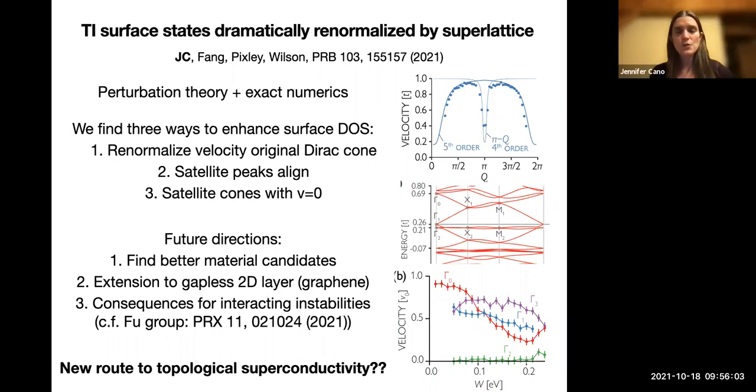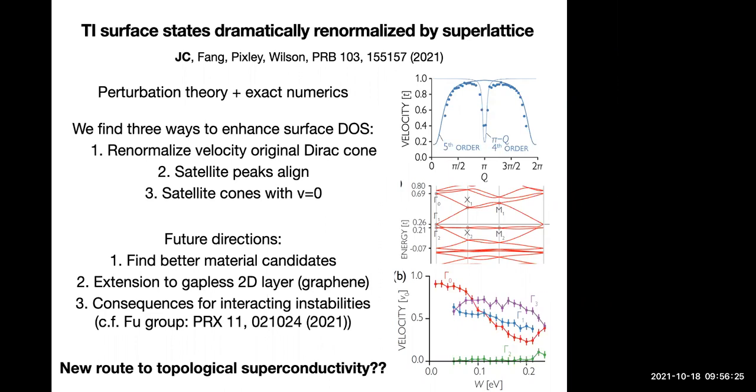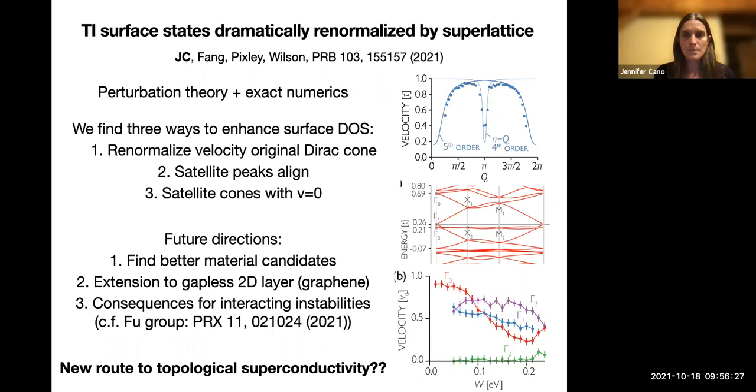Right, exactly. So we have some results in this direction already. It's a different calculation where instead of having a potential, we would actually keep the interlayer coupling. So you tunnel TI to say graphene and then back. And so that's why we expect that you would get something different, because it's actually a different model. It's a more coupled model. And so it's more similar to the Bistritzer-MacDonald model. It has more Dirac cones involved. So that's why we wanted to do it.